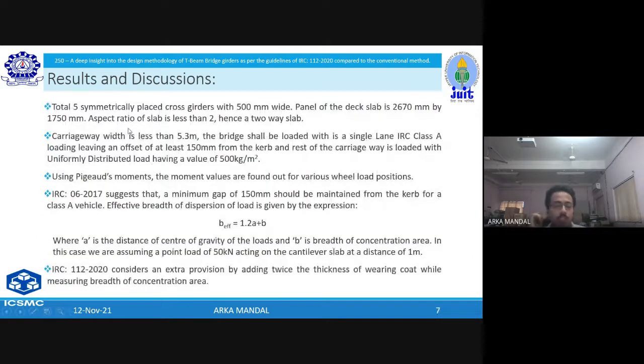Now, as shown in the previous figure, the width of the cross girders is 500 mm, and the deck slab is 2.67 meter by 1.75 meter. Since the aspect ratio is less than 2, it will be treated as a two-way slab. As previously said, the width is less than 5.3 meter, and so it shall be loaded with a UDL of 500 kg per meter square as specified by IRC 6.